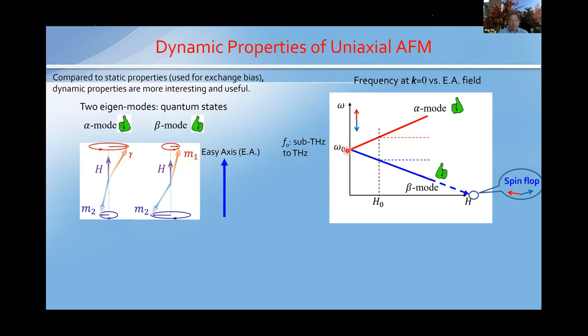The energy of the two modes can be lifted by applying a magnetic field along the z-axis. If you apply a large enough field, this collinear anti-parallel configuration can be stabilized by the so-called spin flop transition when the field reaches the spin flop critical field. So this left-hand mode has a relatively lower energy than the right-hand mode.